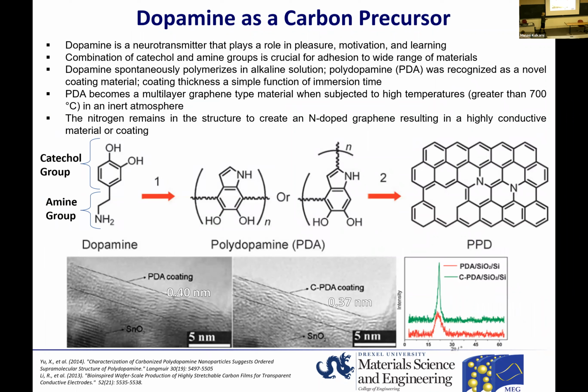So what kind of molecule would be a good precursor for carbon? We learned that dopamine, that many of you know as a molecule of everything, right? This is a motivation molecule that is produced in our brain, usually when we achieve something, when we feel good about our achievement. But the same molecule is also a great precursor for carbon synthesis. And for us, this molecule is attractive because it also has a positively charged amine group, so it can react with our negatively charged vanadium oxide layers. And it already has this aromatic ring, which essentially forms a unit block for the carbon structure formation.